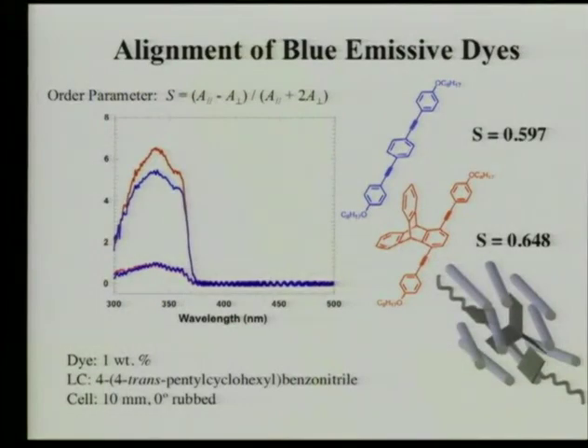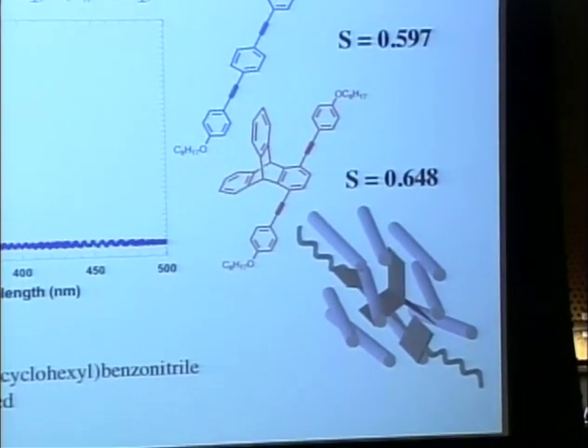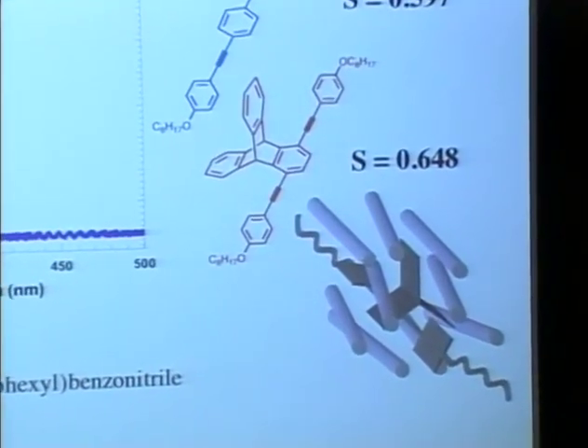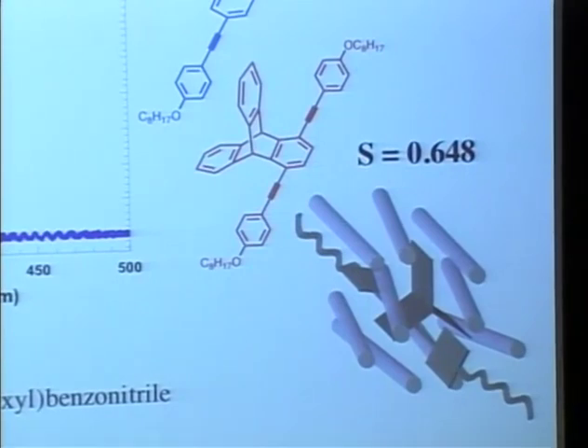But these molecules are chromophores, so it's very easy to monitor how well they align by just doing absorption spectroscopy. And you find that the red molecule aligns better because it has this little stabilizer wing on it, and things are threading through it, and it's feeling its surroundings. So it's like a compass needle inside this liquid crystal. And it actually is looking and knows which way to direct, although the liquid crystals are fluids, so they have essentially a mosaic of orientation. They have one global director, but locally they're very disordered.